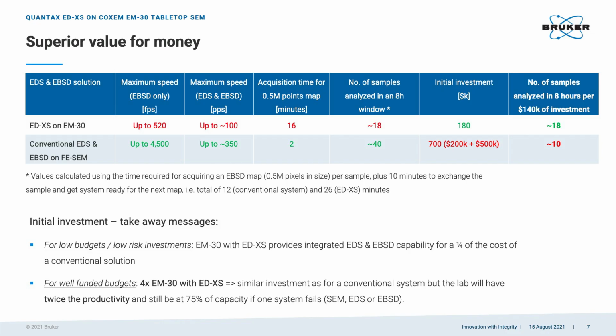detector. But now, if you consider then an 8-hour work window per day, how many samples one could analyze in one day? And the difference is not 8 times more samples, because you need to vent the microscope, exchange the sample, pump the chamber, and prepare the system to launch the next map. And that for a reasonably experienced technician would take, let's say, 10 minutes. And then that means with ED-XS, a technician could analyze 18 samples in 8 hours, and 40 samples with a conventional EBSD system.